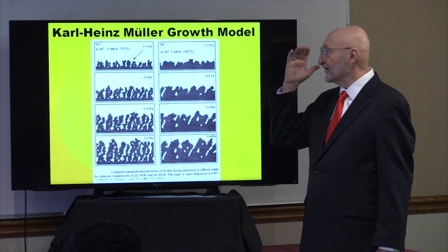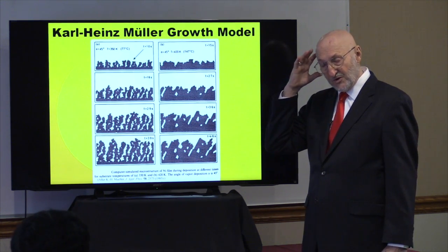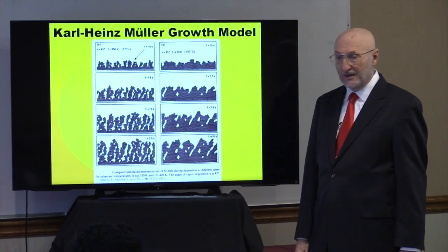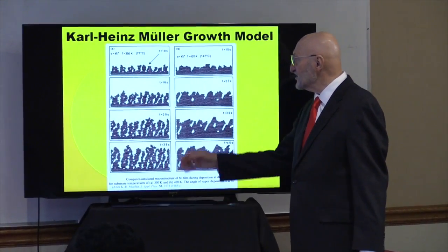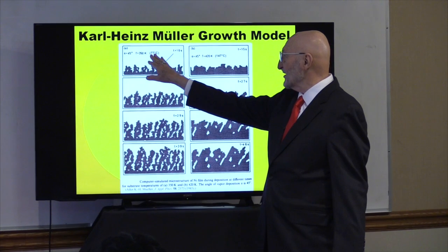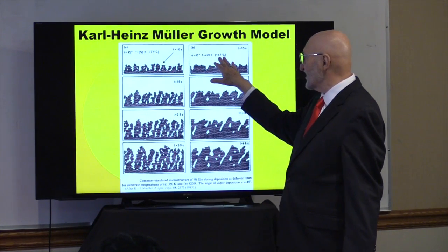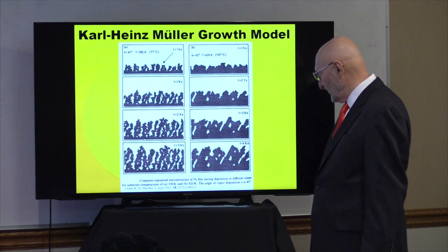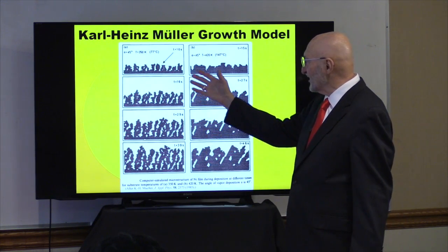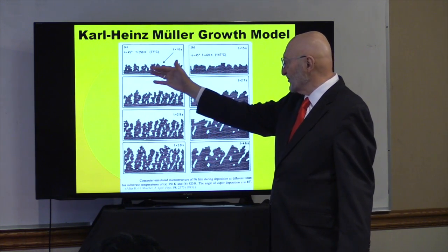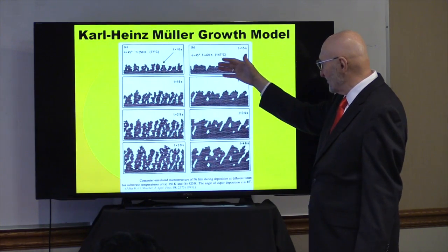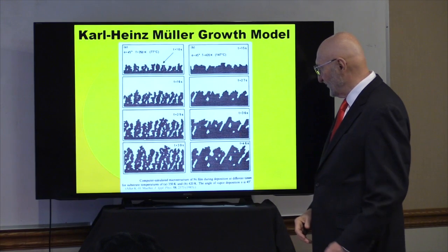Here's some computer simulations by Karl-Heinz Müller in Australia, where he's doing this at 77 centigrade and this at 147 centigrade, and he's depositing nickel. And so at this lower temperature, the nickel deposits this way, and at a higher temperature, it deposits more densely.